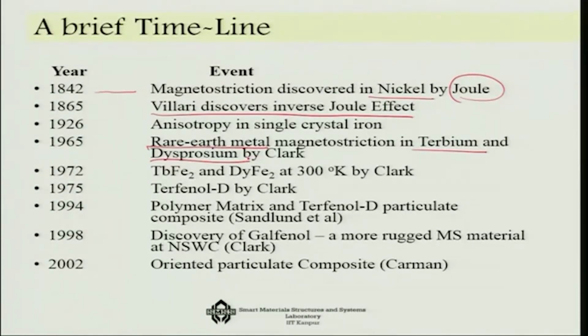Later on, in 1972, it was found out that instead of using pure terbium or dysprosium, if you use a terbium iron compound or dysprosium iron compound, you can actually get magnetostriction up to a much higher temperature. And then on this terbium iron compound, if you add a little more dysprosium, you are going to get a much larger magnetostrictive effect, and that is Terfenol-D, which was actually discovered by Clark. And later on, people found out that if you use a polymer matrix and a particulate composite of Terfenol-D, you can make a nice composite out of it, and you can give nice shapes to the system.